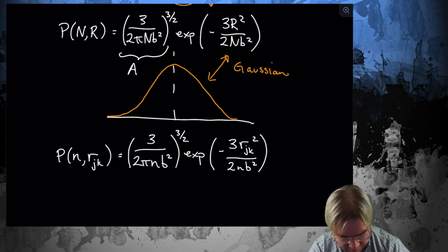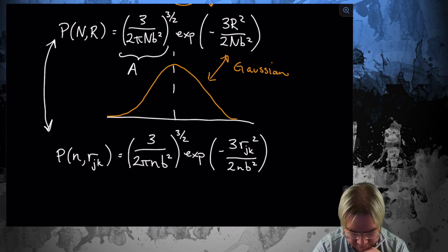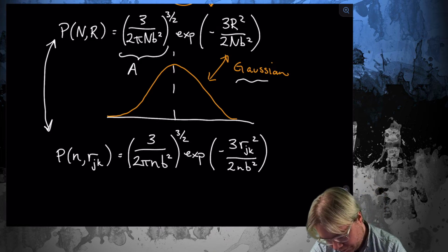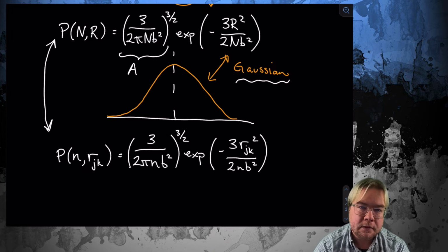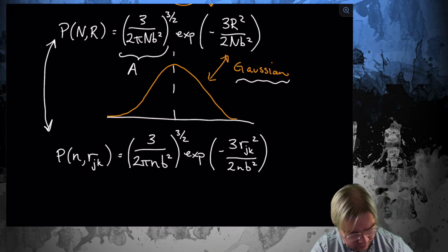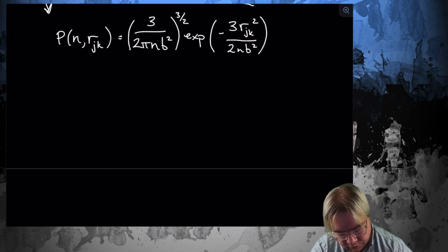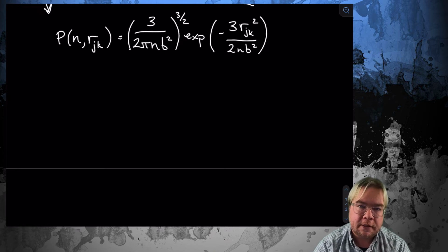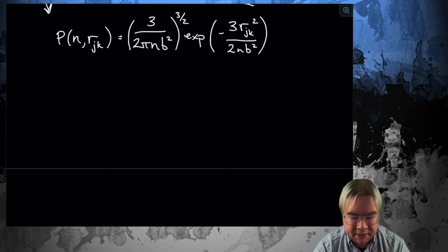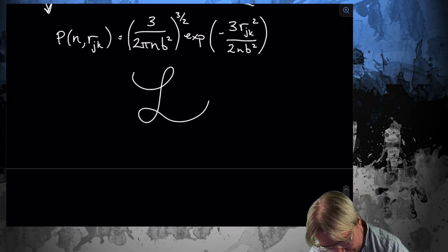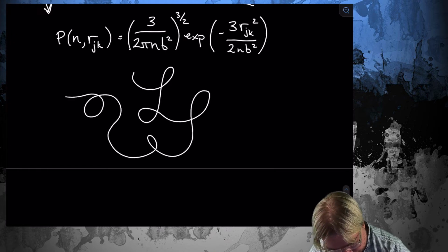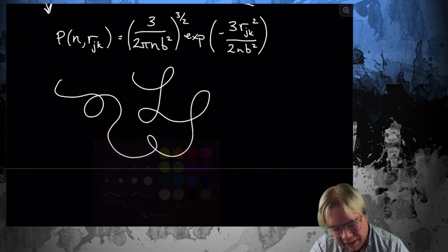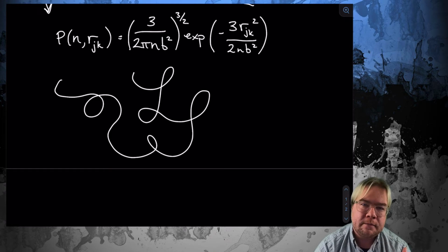And remember that self-similarity is what links these two things together, and that they are both going to give you Gaussians. So we get a Gaussian chain. So if we just look at the second expression for the smaller region inside of the polymer chain, what does this mean? It means that if I look at the polymer chain, let me specify 2 monomers.